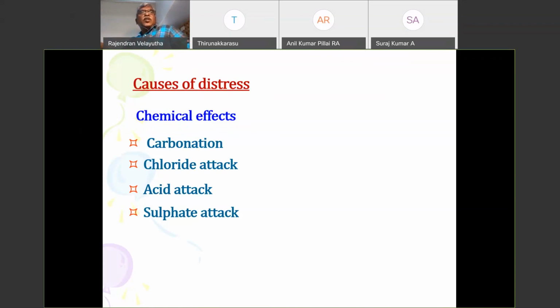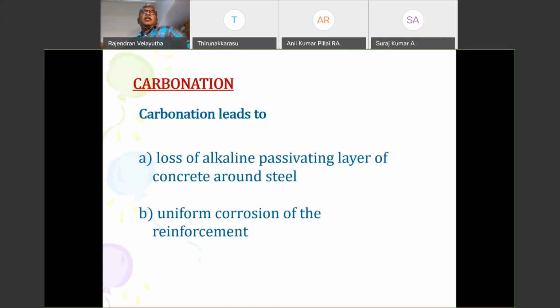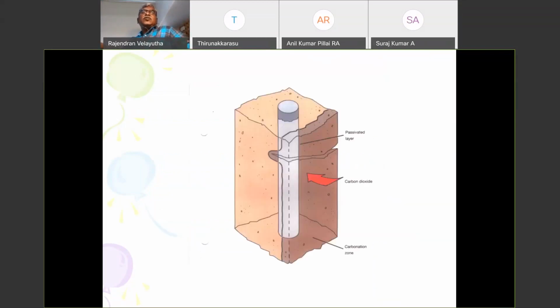And chloride, yes, we know places like Chennai are predominantly affected by chloride, and this chloride corrosion is more dangerous than carbonation. Carbonation is loss of the passivation layer, and the pH value gets reduced. Carbon dioxide diffuses into the cover concrete, and as it does, the pH value comes down. The core concrete has a different pH value, and the cover concrete has a different pH value.